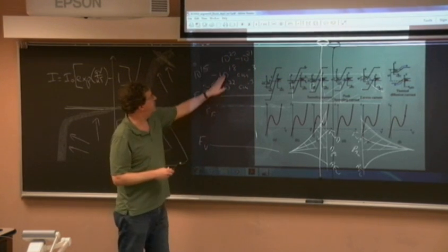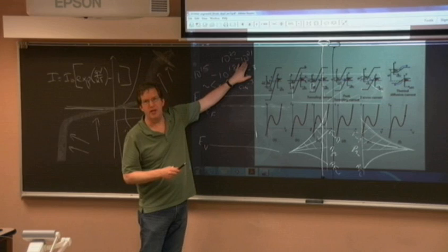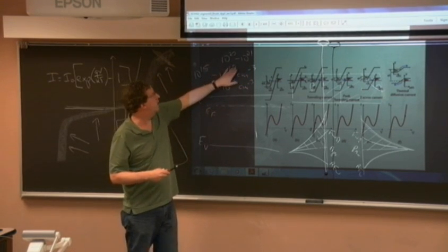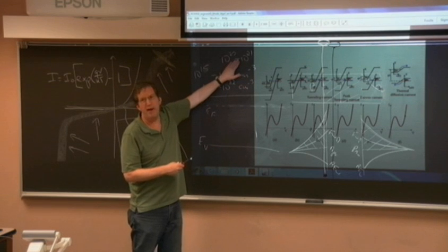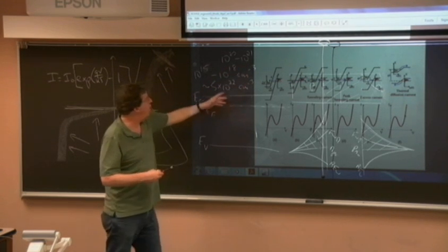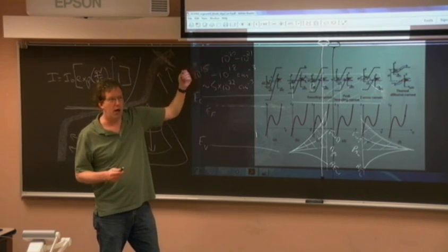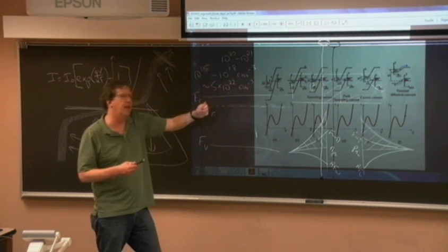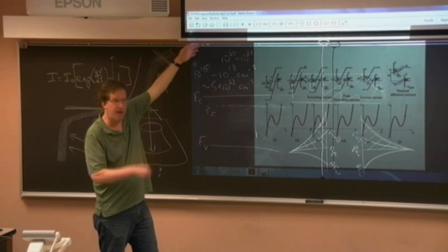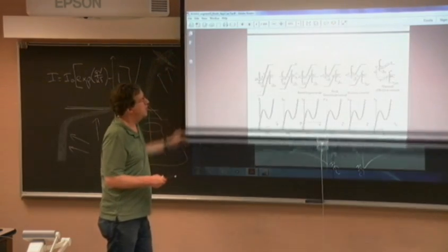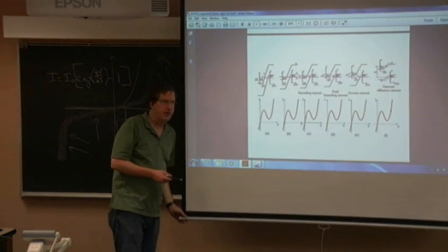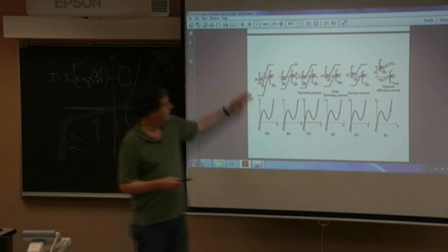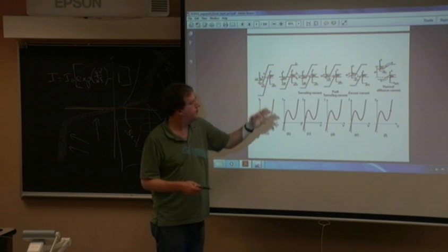In fact, when it gets to 10^20, if it really could get that high, which is kind of unbelievable, usually maybe 5 × 10^19, you can see it's almost an alloy, you'd almost call it, because it'd almost be 1% of the silicon is now boron or phosphorus. And so it's a very hard thing to do, and that's one of the things I've been working on for the last decade or so, is how to do that and do that abruptly.